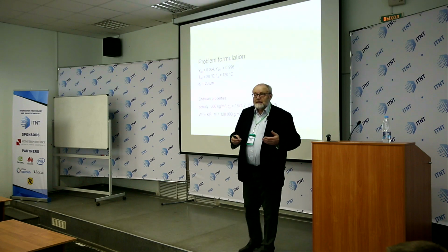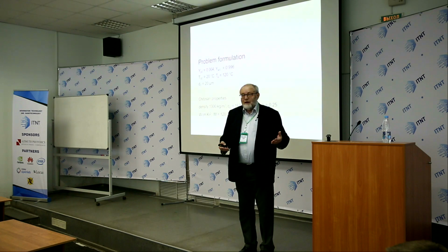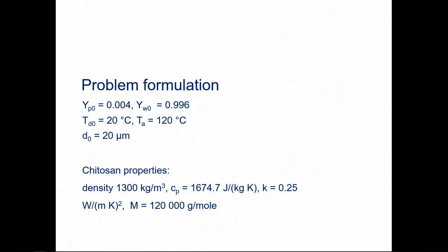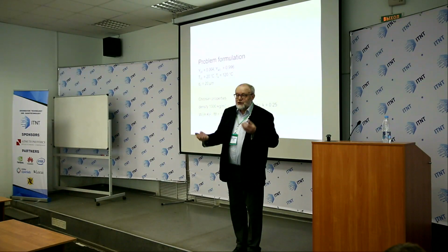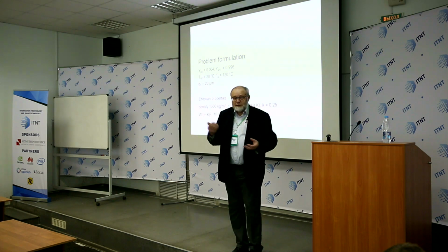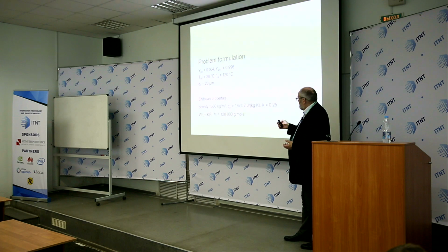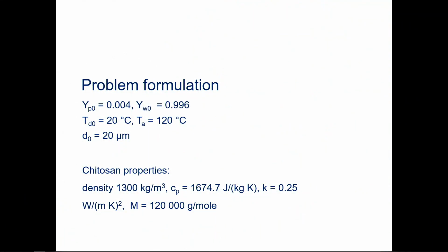Instead, we suggested a different approach. This ensemble of particles can be treated as a non-evaporating fluid. And as a result, the mixture of particles and distilled water can be considered as a mixture of two fluids, two liquids, one evaporating liquid and one non-evaporating liquid. And here we have the formulation of the problem. We have chitosan, which is dissolved in water, and the mass fraction of chitosan is 0.4%, and the mass fraction of water is 99.6%. And so these are initial conditions for ambient air for chitosan, and these are the properties of chitosan.